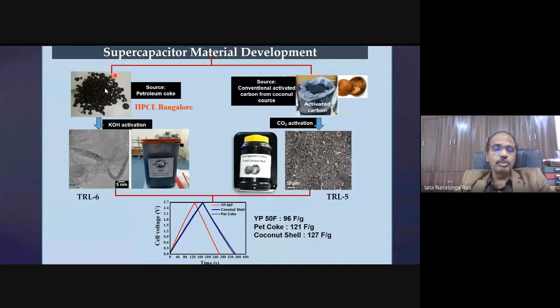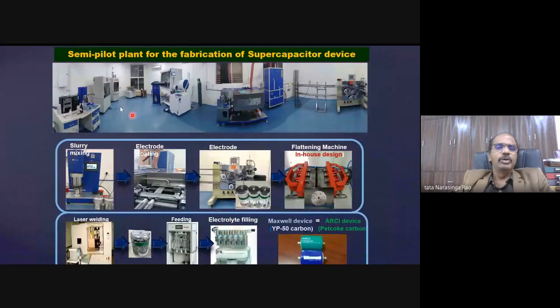But petroleum coke is 90% carbon, whereas with coconut you only get 10 to 15 to 20% of the actual activated high surface area carbon, and here you can extract up to 70%. So now we are working with HPCL, funded with 1 crore, to make this material supercapacitor grade, and we established a fabrication line together with HPCL at ARCI, with all the equipment to make battery and supercapacitor cells. You can see here jelly rolls made, with carbon coated on aluminum foils.